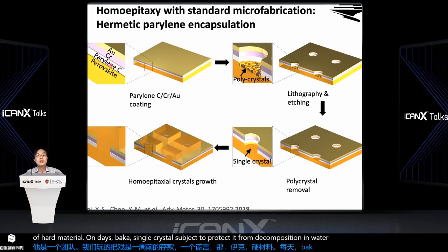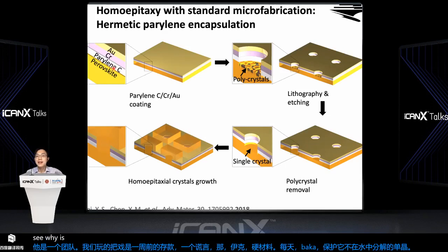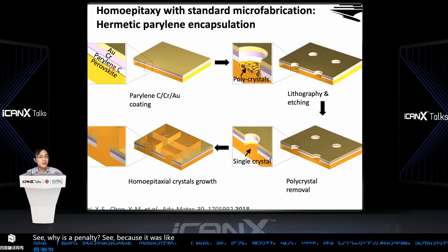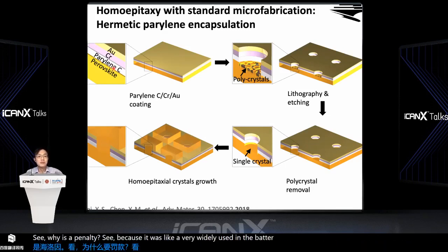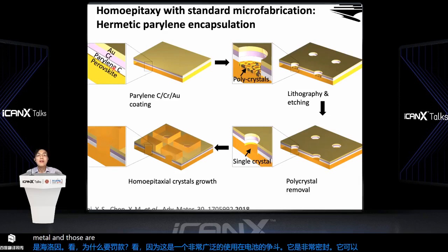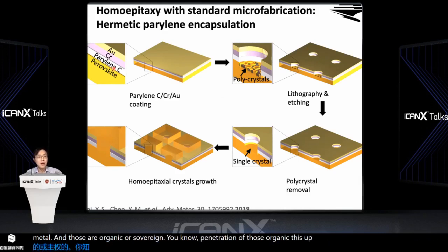And the material we use is Parylene C. Why Parylene C? Because it is very widely used in the battery field. It is very hermetic. It can prevent lithium metal and organic solvents from penetration, and prevent water molecules and oxygen molecules from reacting with them, right? So this material is a fantastic barrier for moisture and oxygen.